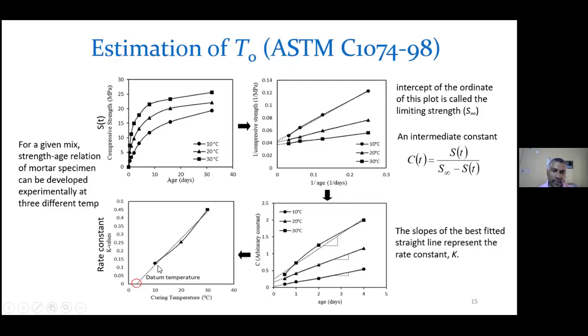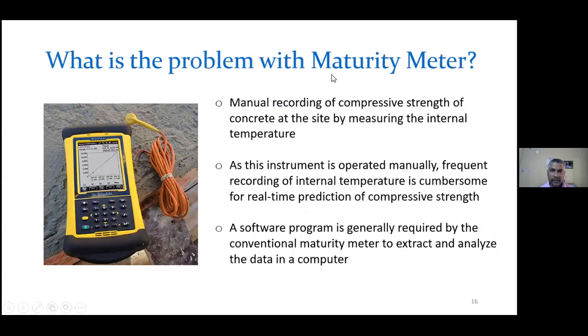These slopes are known as K, the rate constant. Now I plot the rate constant for 10 degrees, the rate constant for 20 degrees, and for 30 degrees. I make a best fitted line, and it cuts the abscissa at a point, marked here in the red circle, and this is taken as the datum temperature. This procedure is outlined in this code, so we can find out the datum temperature.